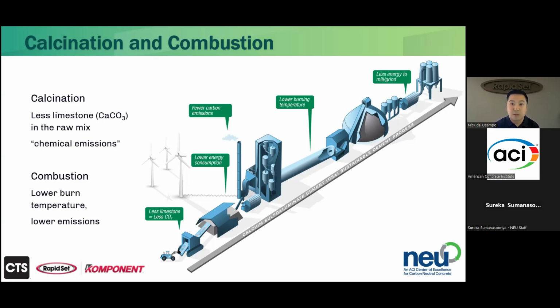The other thing is combustion. As I mentioned with alite, the burn temperature of CSA is lower than alite. Where a Portland cement kiln typically requires 1500, 1600 degrees Celsius for the reactions to occur, the reactions that form CSA happen at around 1280 degrees Celsius. So the burn temperature required is lower, which means less fuel needs to be burned, and that results in lower emissions.